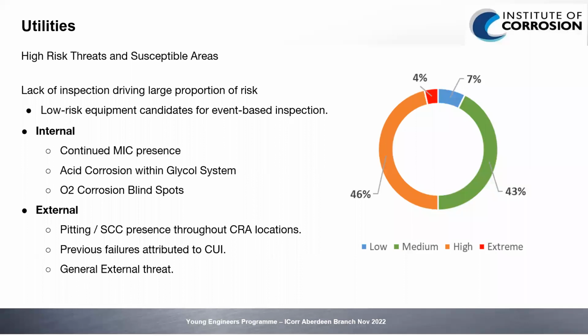In terms of main threats, internally, we're seeing a continued MIC presence throughout the utility system as well as the process. We've also got the potential for acid corrosion within the glycol system. There was a glycol leak in 2020. At the time, this was attributed to CUI. Based on the fluid and the rich glycol pipework, acid corrosion is expected. However, inspection data in this area is limited.